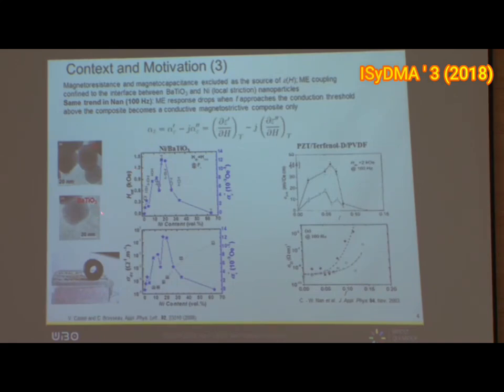When you look at the cross-coupling, it's very important to realize that this effective parameter is very well correlated to an internal local parameter, which is the internal field measured by FMR, ferromagnetic resonance. This is a good indication that what you measured has some microscopic coupling origin.